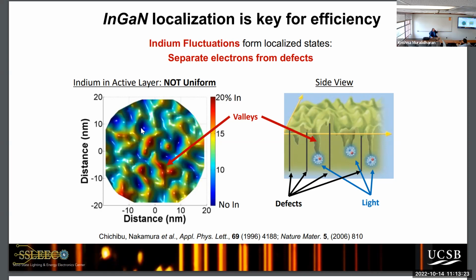So if we made a quantum well, you would get huge fluctuations in the indium. What that does in the energy gap state is you would get a very rough surface. So normally semiconductor scientists would tell you, you don't want to get a rough surface, but it turned out to be the exact opposite. You actually want an alloy because the alloy would then provide a quantum well here, or even a localized quantum state. This isn't just a quantum well, this is localization in all 3 dimensions. So this is what's called nanotechnology. It's basically a quantum box. So you get a quantum box here in this little region. So when you throw electrons and holes in from the battery, rather than go anywhere, they fall into this well. And this is just like freshman quantum mechanics when you solve for the finite potential well. We have now created a finite potential well.